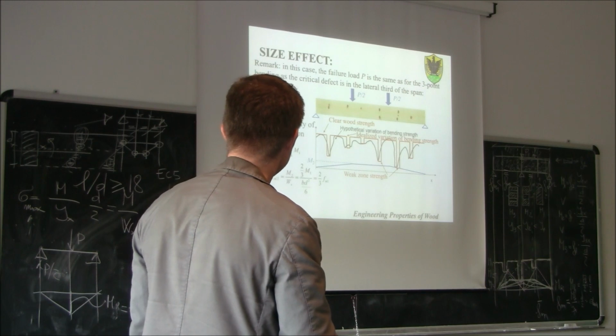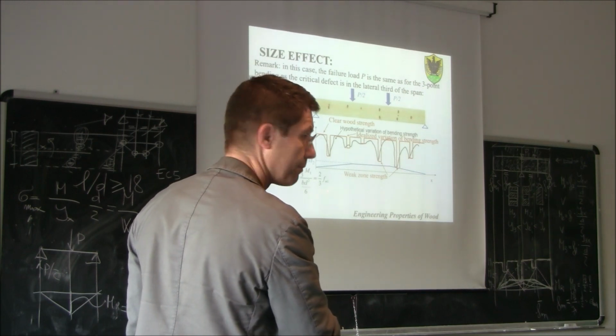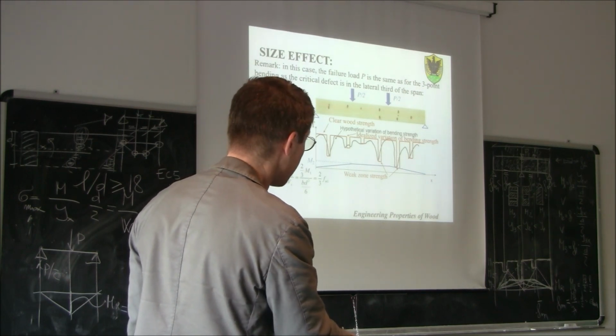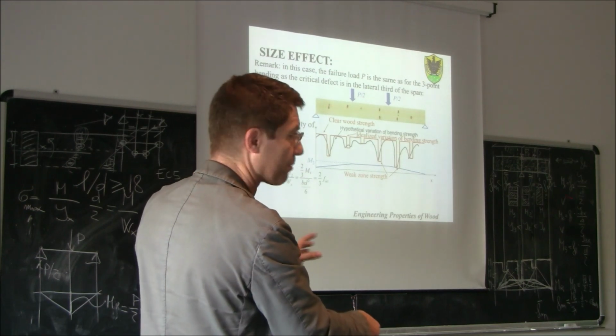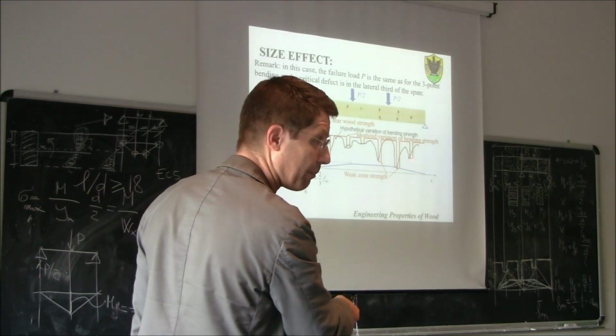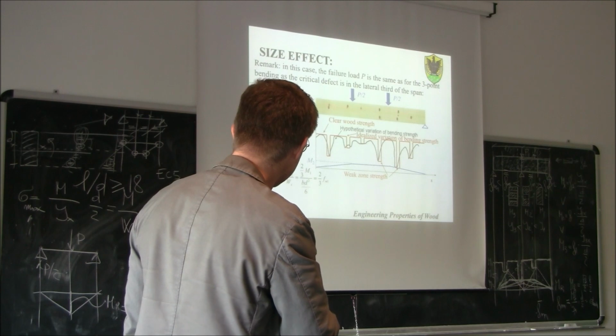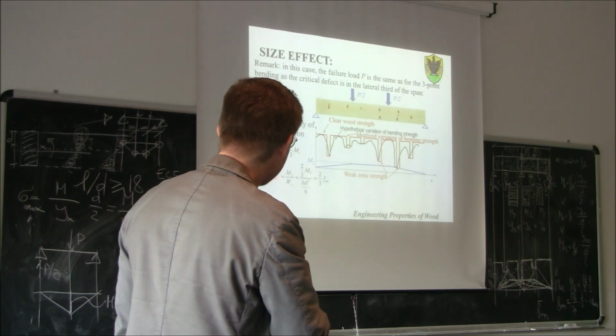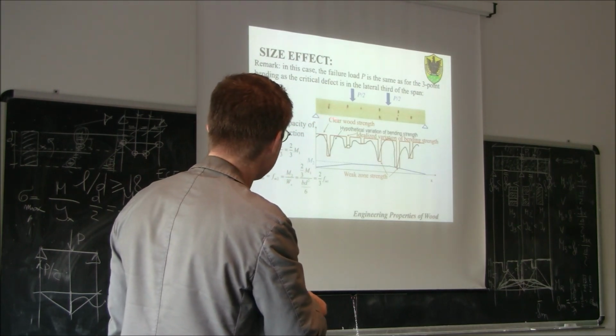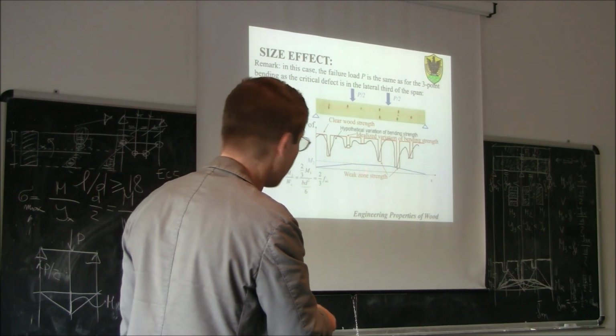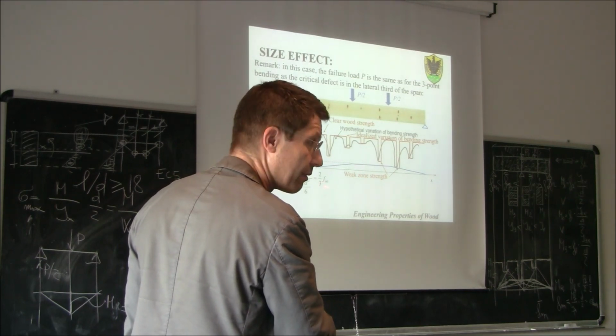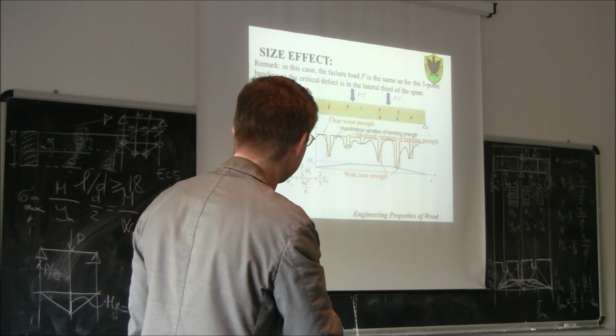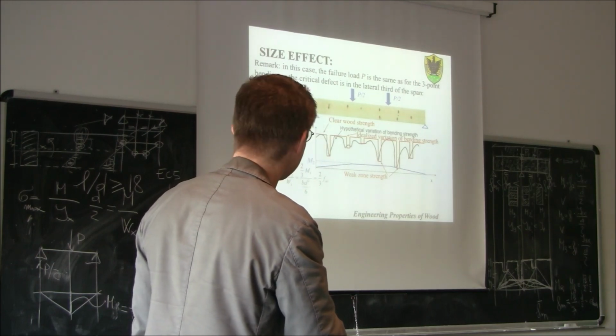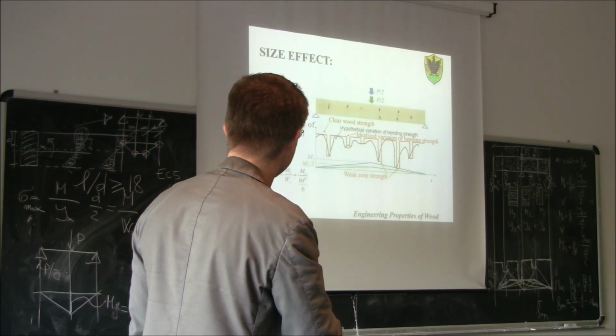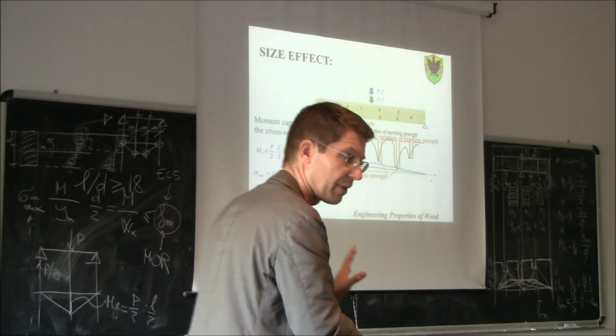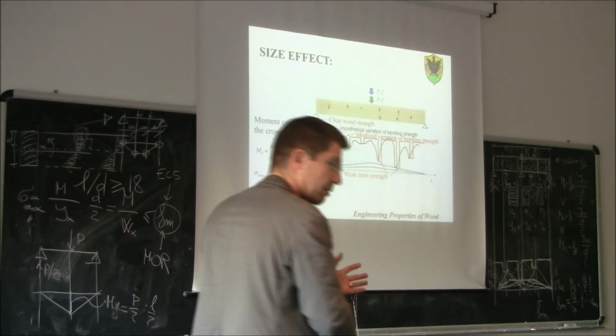2-point bending moment. You see, in this case, if we compare, we said before there was larger, smaller, etc. If you look at this specific case, we can demonstrate that the FM2, by testing the same specimen with 2-point loads, we would get an apparent strength FM which would be 2/3 of the strength that we would get with this load configuration. 2/3, so it's a huge difference. 33%.